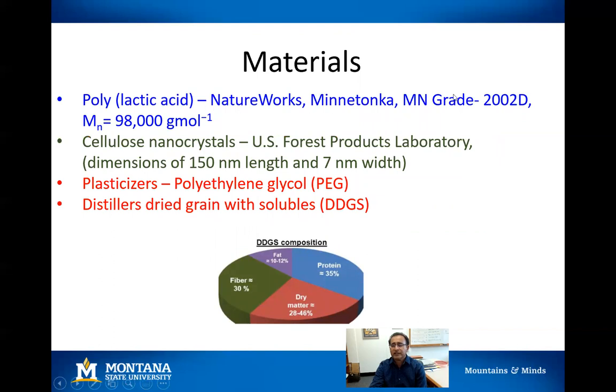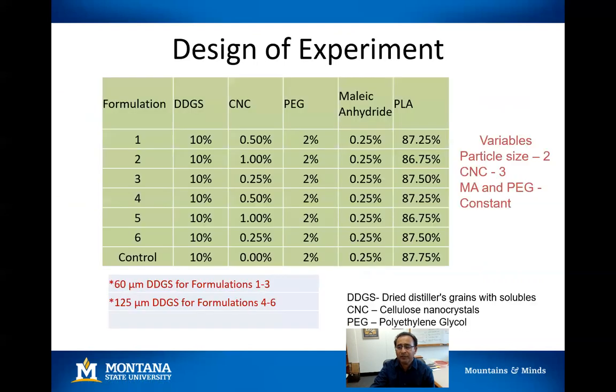Again, the materials: polylactic acid, that was a 2002D grade with a molecular weight around 98,000 grams per mole. Cellulose crystals were supplied by the US Forest Product Lab. The dimensions were around 150 nanometer in length and 7 nanometer width, and they were derived from softwood through acid digestion. The plasticizer we used in this project was polyethylene glycol, and obviously another filler, distilled dry grain with solubles. So it's important to look at the composition of DDGS. DDGS has around 10 to 12% fat, which acts like an oil or a plasticizer, 30% fiber, and then we have 35% protein. So it's a good filler for composites.